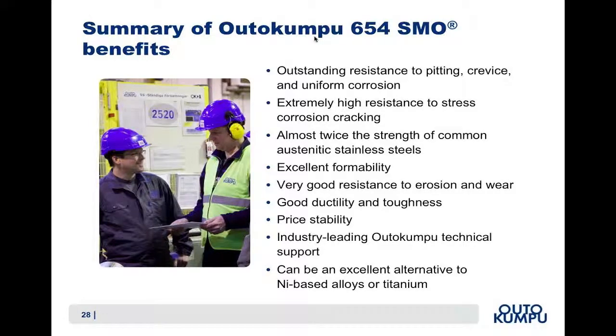So let me summarize 654 SMO and its significant benefits. It has outstanding resistance to pitting, crevice and uniform corrosion. It's got very high resistance to stress corrosion cracking. It's almost twice the strength of common austenitic stainless steels. It's got excellent formability, very good resistance to erosion and wear, good ductility and toughness. Price stability is extremely good. And then you have the industry-leading technical support from Outokumpu, all of which means it can be an excellent alternative to nickel-based alloys and titanium grades.